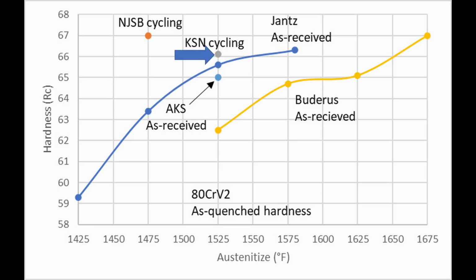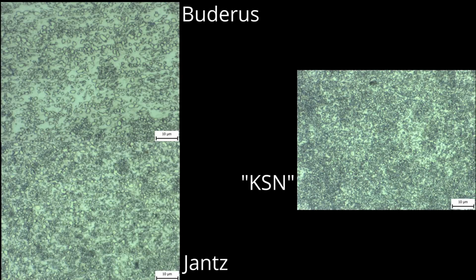The KSN cycling used my own recommended normalizing and annealing. Though the cycling procedure I performed did not start with forged steel, showing that improved microstructures can be achieved even without forging. We found that this resulting hardness difference also lined up with the starting microstructure. When we looked at the steel under the microscope after polishing and etching, we found that the Buderus material had coarser carbides than the material supplied by Jantz or Alpha Knife Supply, and those were all coarser than the steel that got my KSN cycling, Knife Steel Nerds cycling.